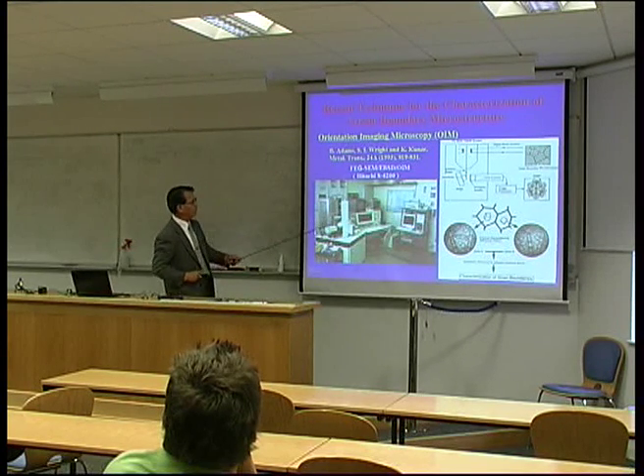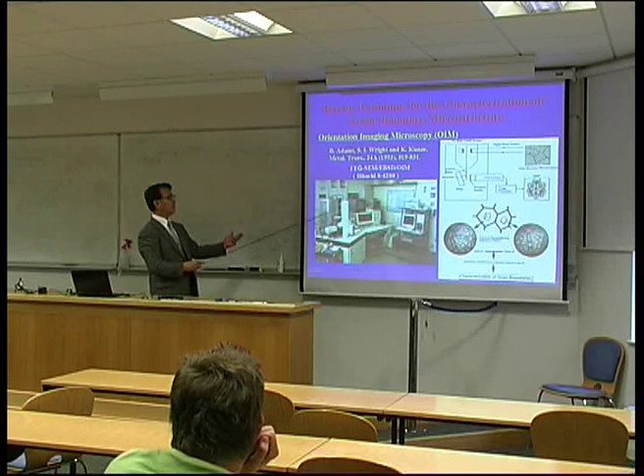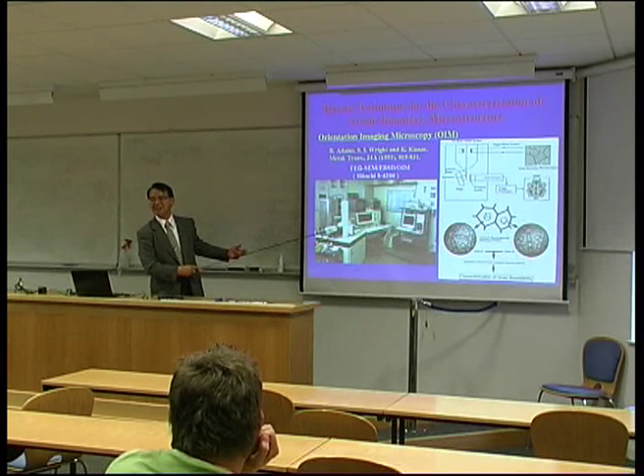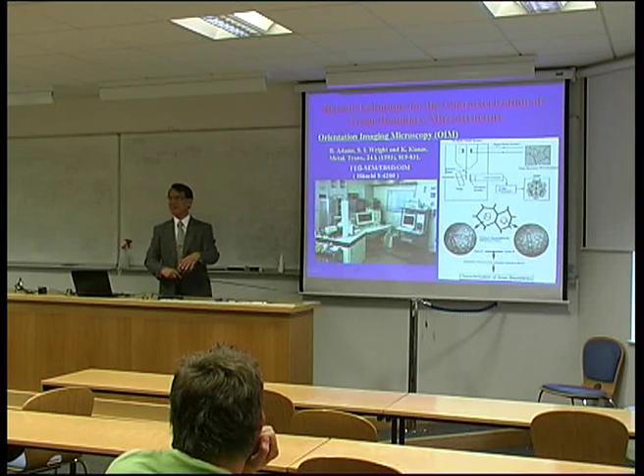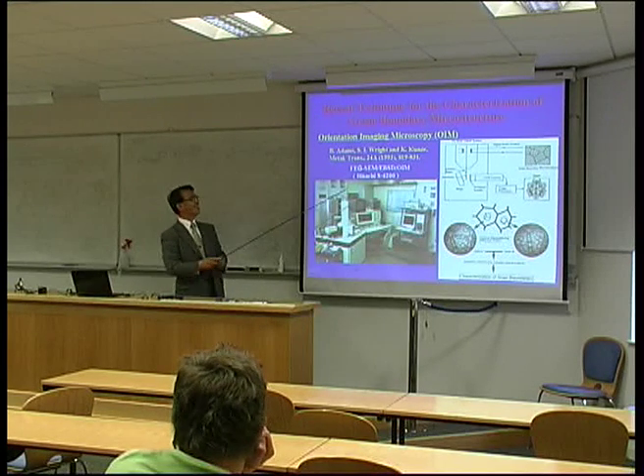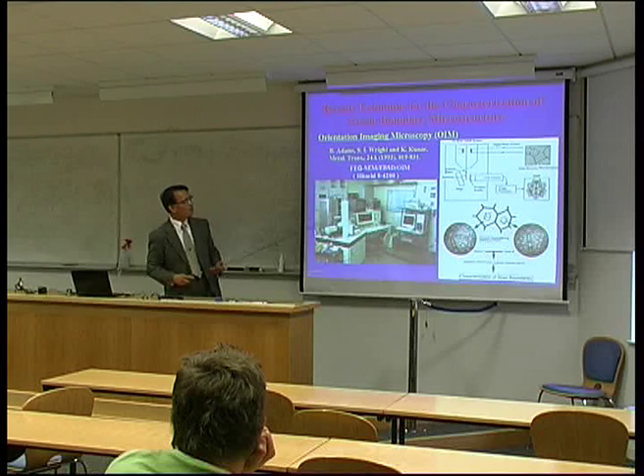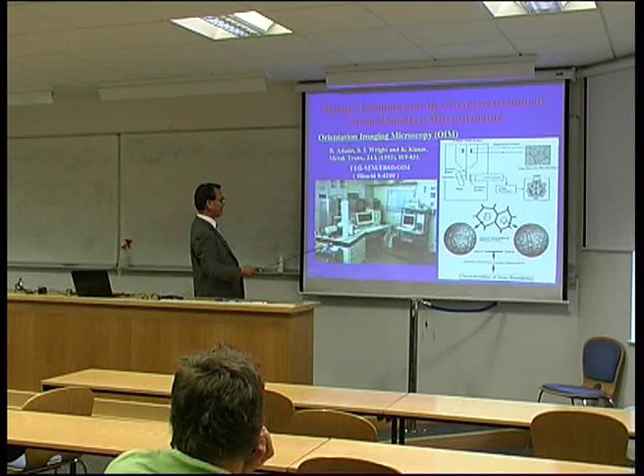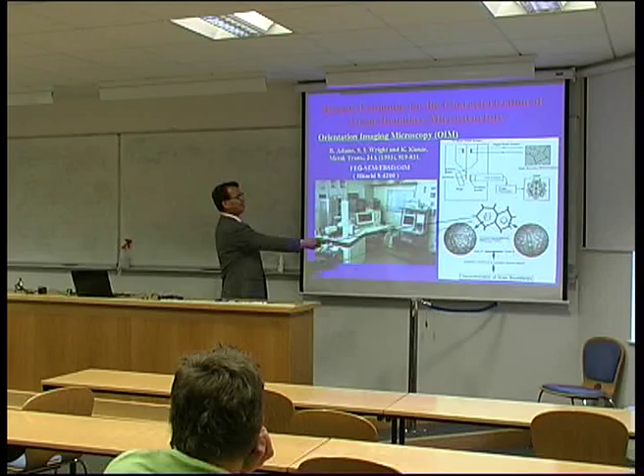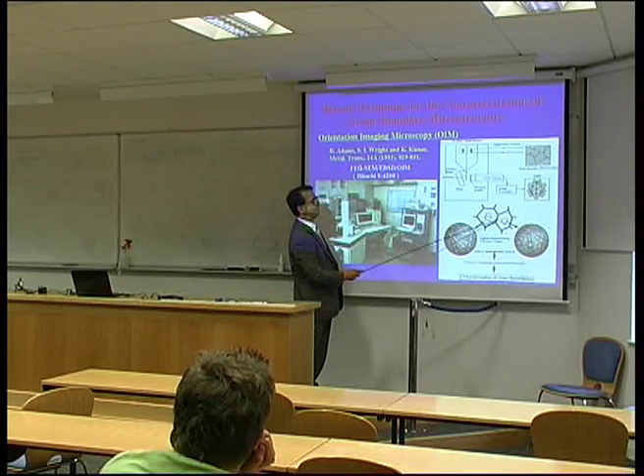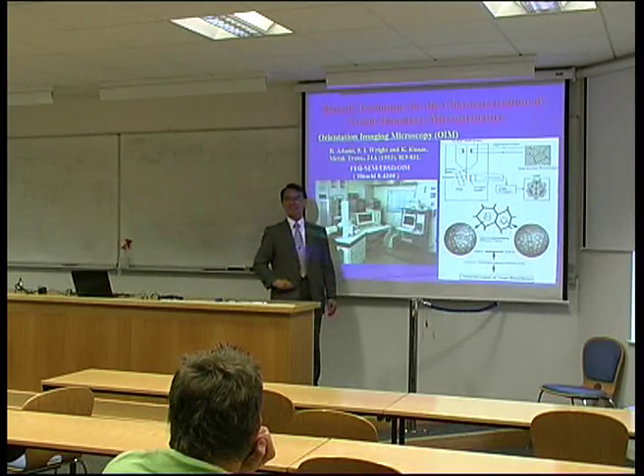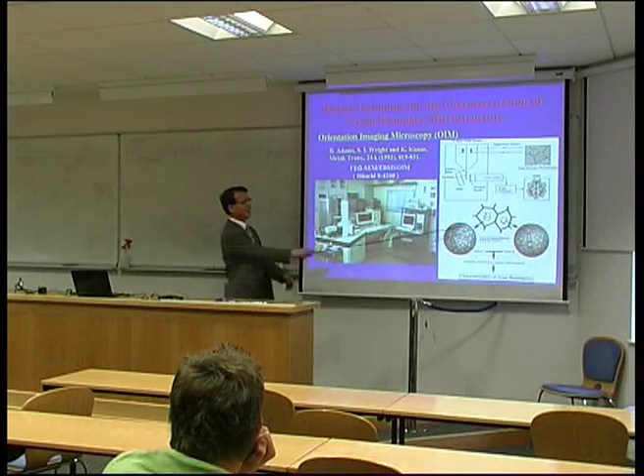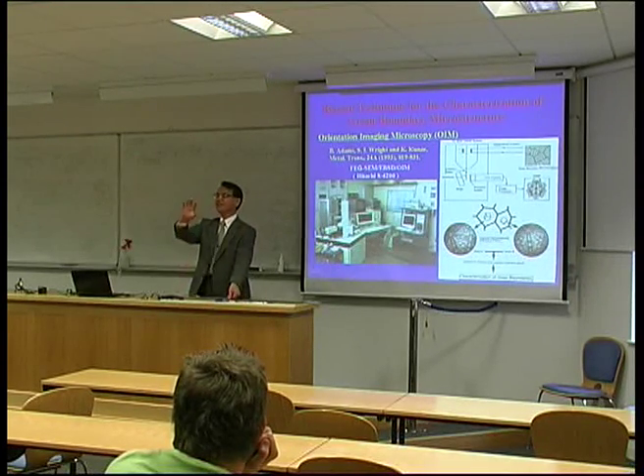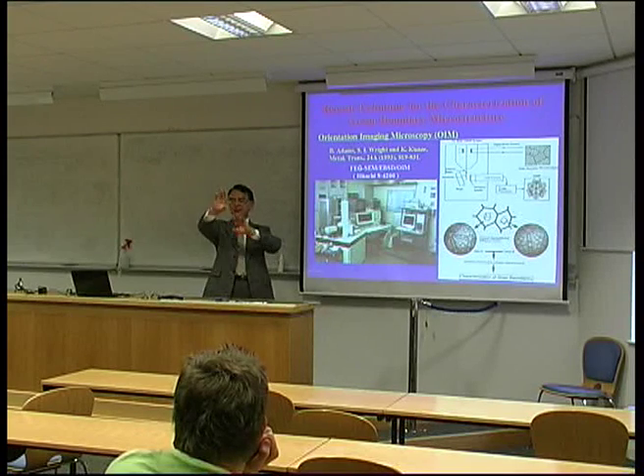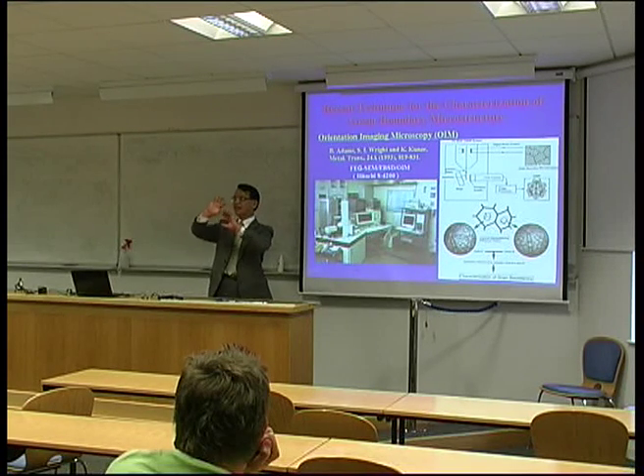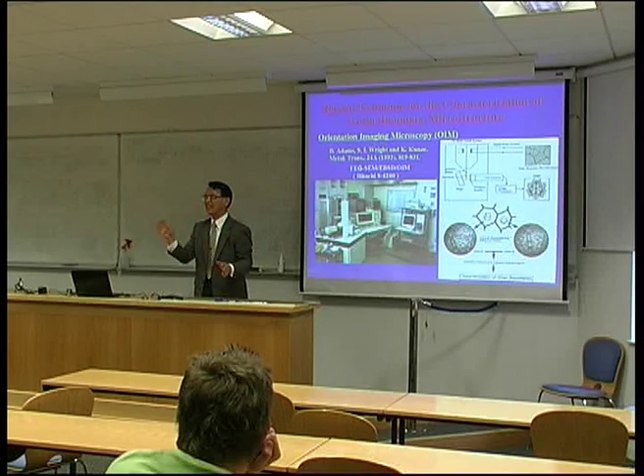And now our machine is getting older. Maybe here you have the most modern EBSD microscope, I hope. But anyway, the principle is the same. Taking the pattern from the neighboring grain, we can characterize the boundary, the relative orientation. And then we can draw the map, and how the different boundaries are connecting to each other very easily.